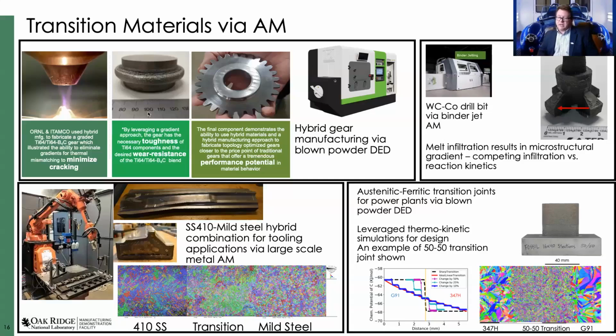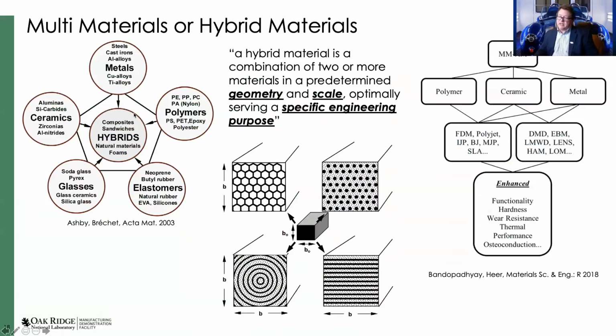In large-scale metal deposition, we've shown how we can take a mild steel and then fuse down a stainless steel on the outside as we build these materials. We've also shown transition joints between austenitic and ferritic materials, typically very difficult to join, that through grading the compositions, you can actually get to a solution where you join those together. I have different examples looking at multi-material and what type of geometries, but I'm going to stop at that point. I wanted to at least introduce these subjects to you and show that there are opportunities through additive to think about multi-material solutions, not just in the same class of materials, but even things like ceramics and metals, ceramics and polymers, or metals and ceramics.